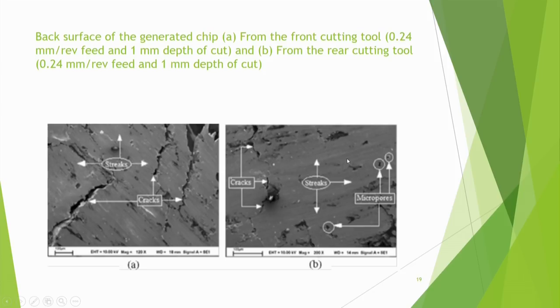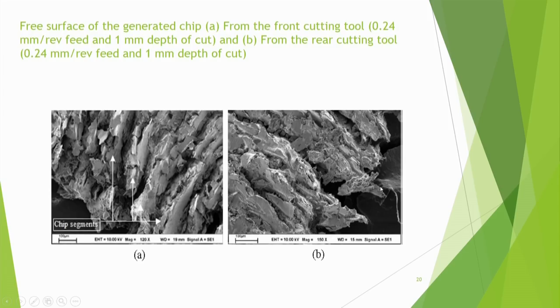In fact, he took the feed quite large, 0.24 mm per revolution is a high feed, and 1 mm depth of cut. Here you are seeing that he got the formation of cracks, and there are streak lines, that means due to rubbing of the chip, you get some parallel marks, those are called streaks. Here also cracks, streaks, and some micro pores have been shown. And then the free surface of the generated chip is also shown here.